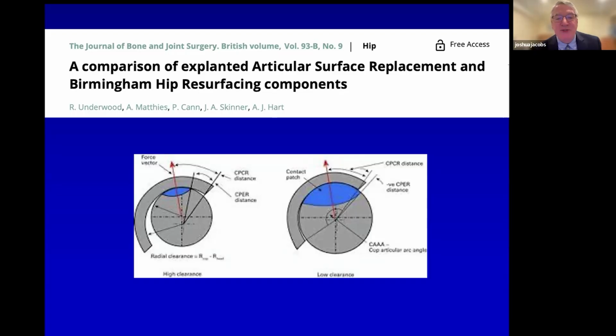So it turns out that in these systems, if the contact patch, which is in blue, overlaps with the edge of the acetabular component, the socket component, that leads to a phenomenon called edge loading, which results in a tremendous amount of wear and excessive or accelerated debris generation. And as we'll learn shortly, it's the debris generated from the implant that was determining the biological response of the local tissues and ultimately the bad results.